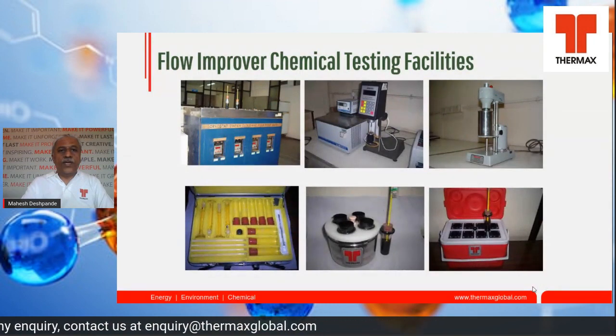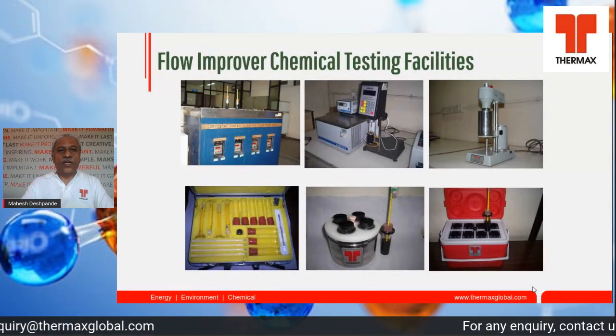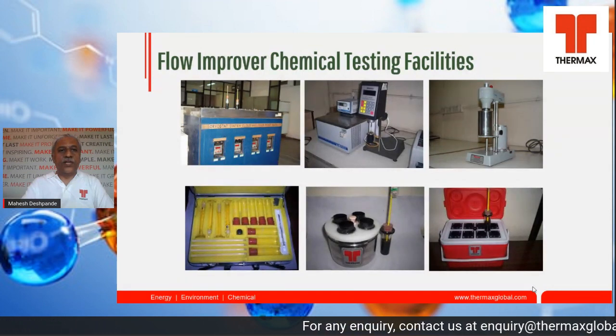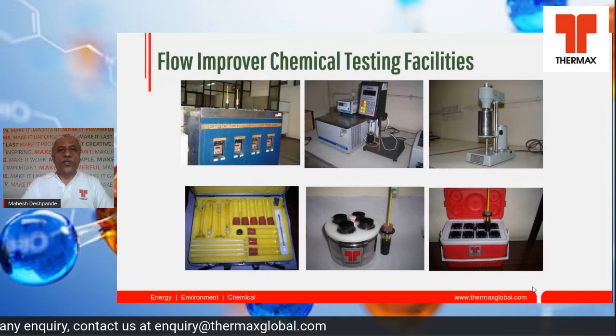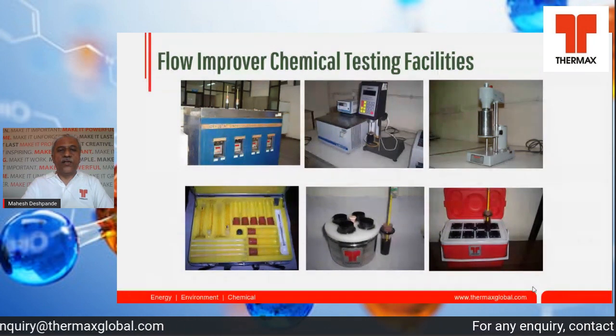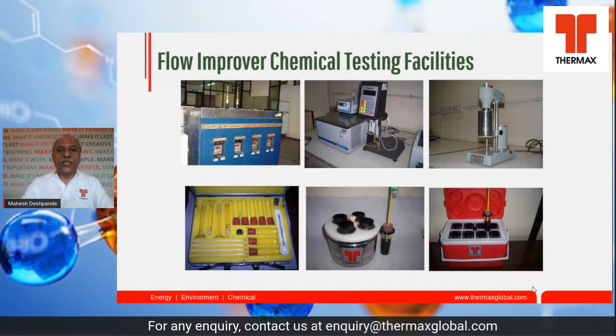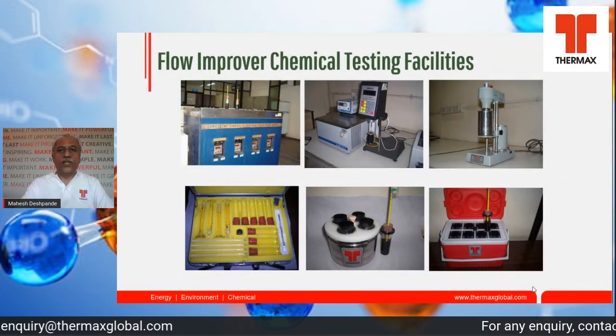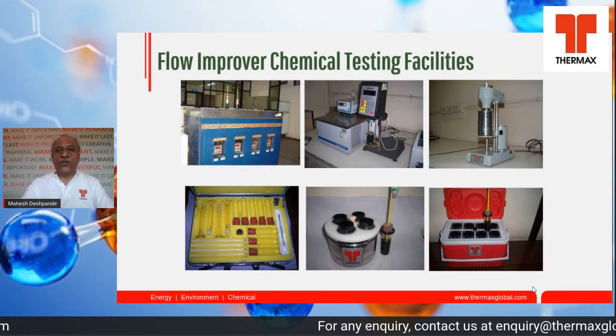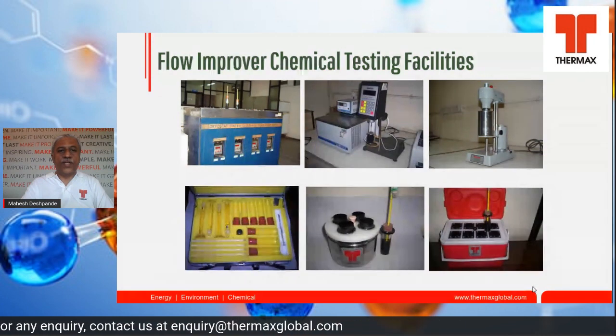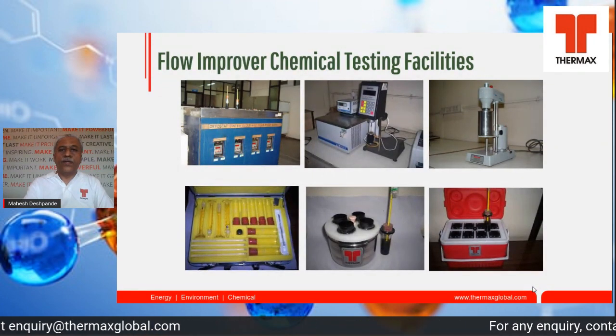These photographs show the flow assurance testing kits in our laboratory. First one is the cloud and pour point bath, ASTM D97 specified. Then we have Brookfield rheometer to check the viscosity at different temperatures. We can set the cooling cycle and see the viscosity at different temperatures at half a minute interval. Third one is the Fann viscometer, mainly used for plastic viscosity and yield value calculation. And below are some test kits which we can carry to the field and do the testing on the fresh crude.